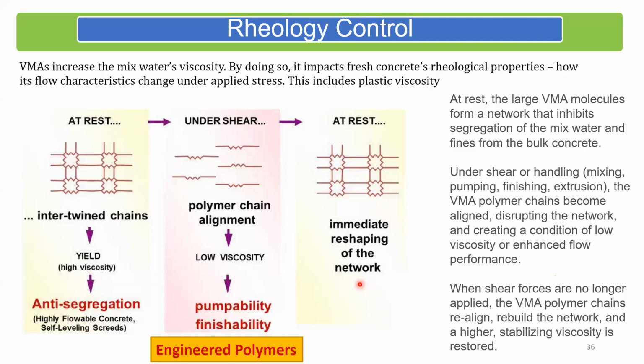And VMAs are also very highly engineered polymers. And the way these polymers work is that initially, when the VMA is at rest, it forms these intertwined long chains, which basically form a network. And this network prevents any movement of water from within the system. If I apply shear, that is, when I start shearing the material, these chains break and get aligned, and that reduces the viscosity. So initially, while VMA is there, it keeps all the ingredients together because it forms this network. It basically holds on to all the ingredients. And if I shear it, once I start pumping it, once I start pushing concrete through the pump, then it gives me low viscosity. So I'm able to pump it very easily. And then when I bring it to rest again, this network is created again, and it does not allow the water and other ingredients to move out. It forms this network very quickly.